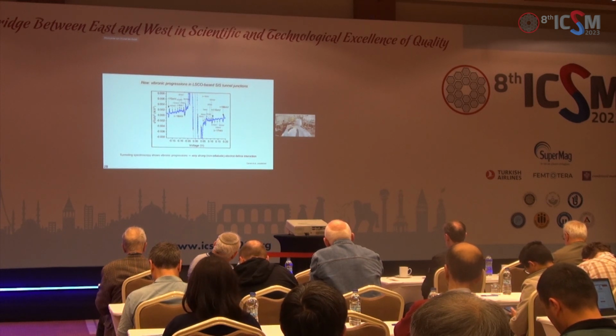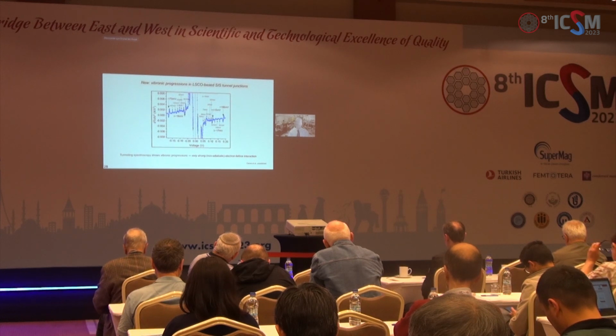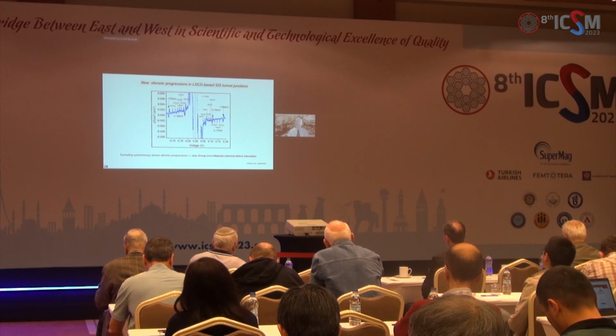optically active vibrations. What we are seeing here is emission of longitudinal acoustic phonons. And I think it happens because you have these lanthanum strontium cuprate electrodes, and then you have charge hopping from one side to the other. And when that charge hops there, you get a charge imbalance instantaneously and locally, and that distorts the lattice, and it has momentum in that direction, so you get emission of the acoustic phonons. And we look at the inelastic neutron scattering spectroscopy, and the energies match. These are the Brillouin zone edge acoustic phonons being emitted along the c-axis.